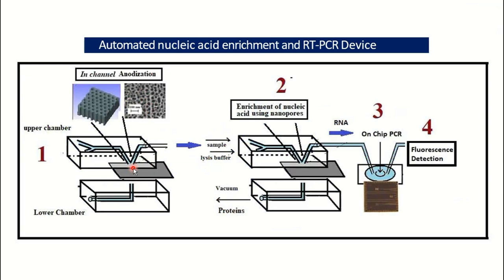But the pore diameter is 50 to 60 nanometers, and the proteins, which are in general in the range of 5 to 10 nanometers, easily pass through these pores and go to the lower chamber, the waste. And once all the proteins have passed to this waste chamber, you move the nucleic acid with the pressure of the fluidic flow. Then it comes to the PCR device, and you can do the PCR.